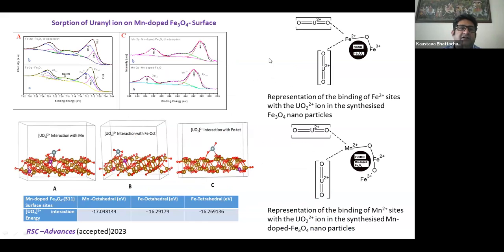Similarly, in this system, what we did was uranyl adsorption upon the Fe3O4 system. What we found was that the amount of adsorption of the uranyl ion was very meager, almost at the ppm level, and the efficiency of XPS is in the parts per thousand limit. So we cannot see uranium there, but how the uranium has interacted with the manganese or iron, that we can see from the iron and manganese.